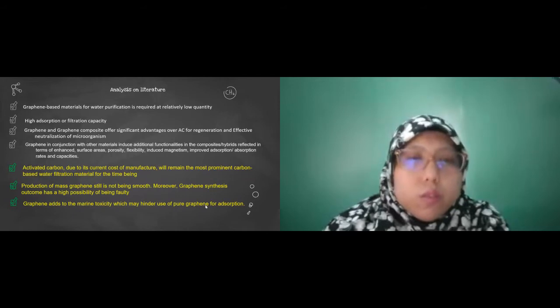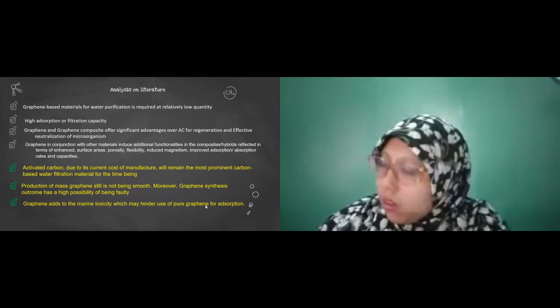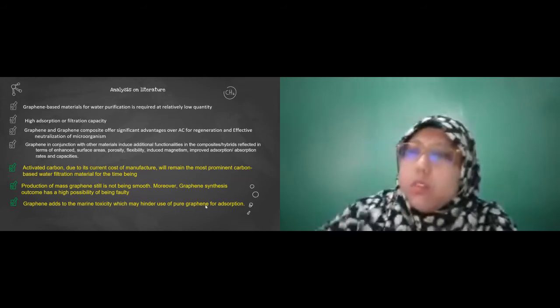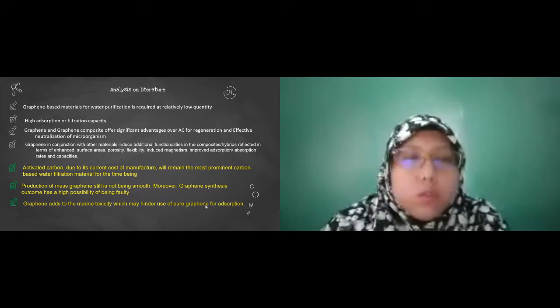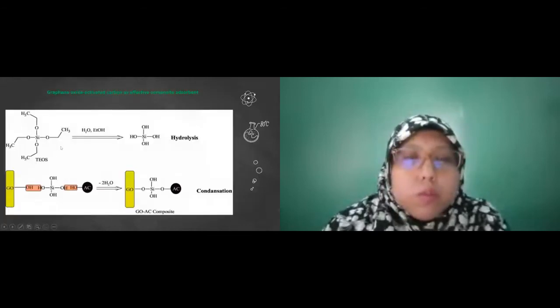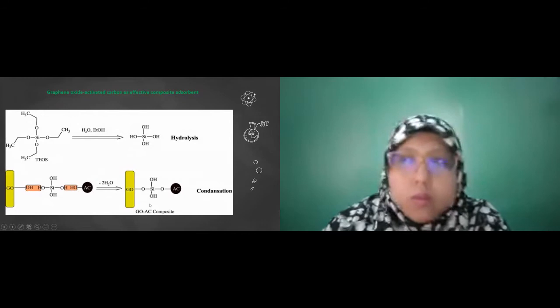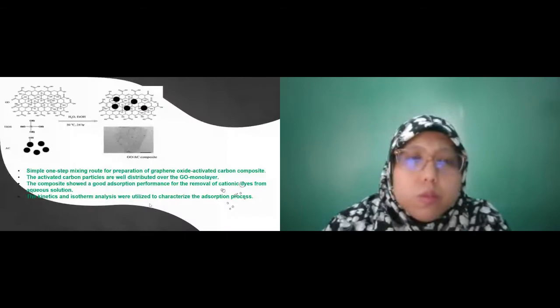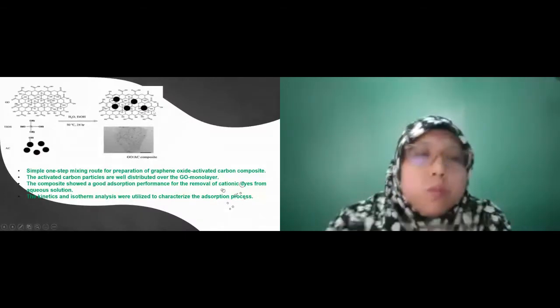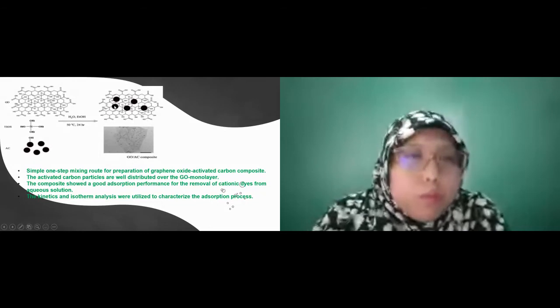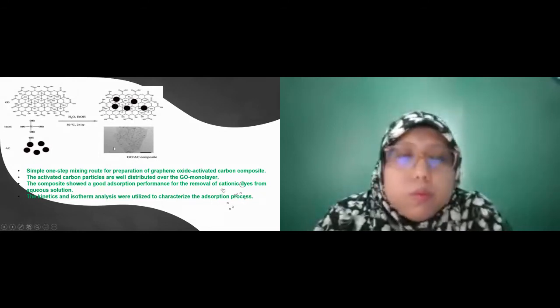This research is already in electrodes, and they have done the composition by these methods, but very little literature is there for adsorption. Here is a proposed one where they are using TEOS, treated with water and ethanol, and then it gets the functional. This functional is mixed with graphene and activated carbon, and together this composite works as a very good adsorptive material. Now this one is supposed to have a schematic structure like this, activated carbon and graphene.